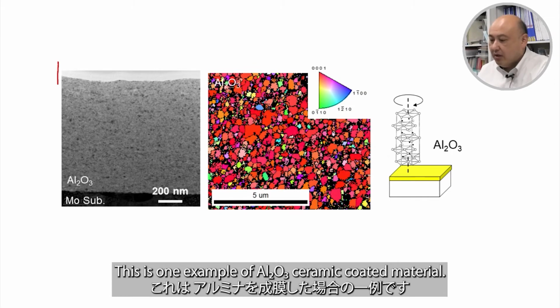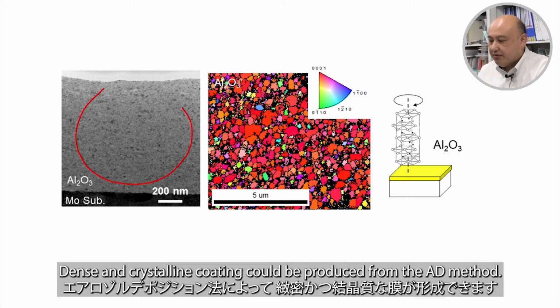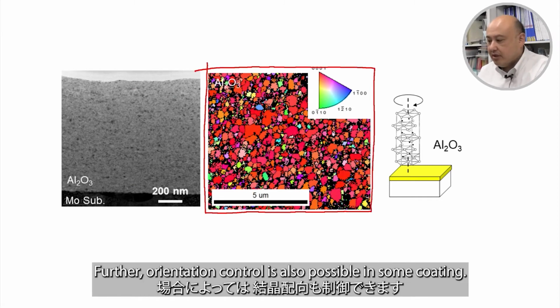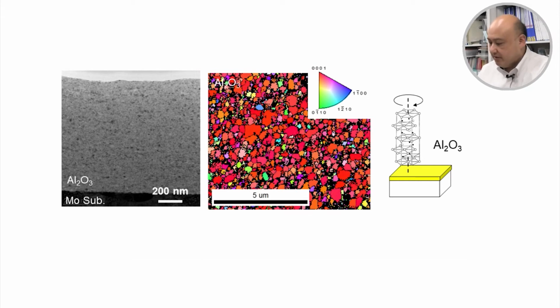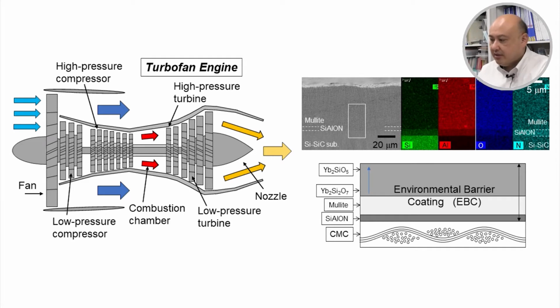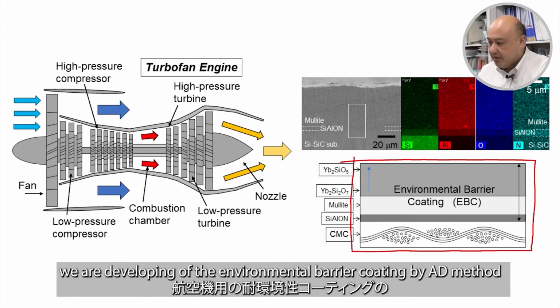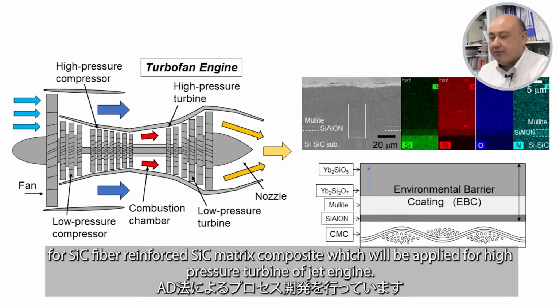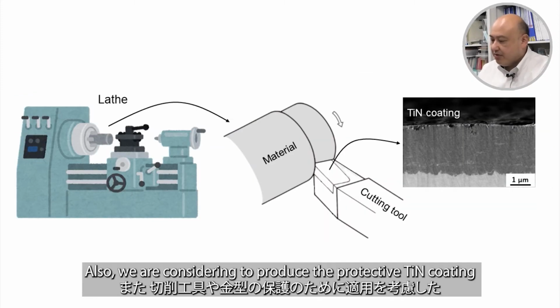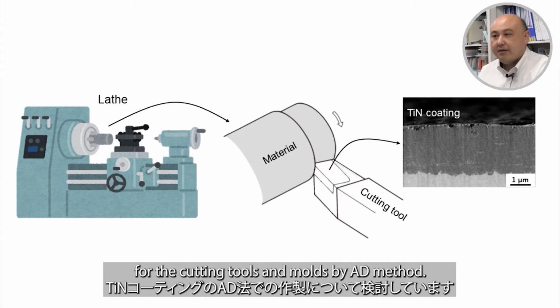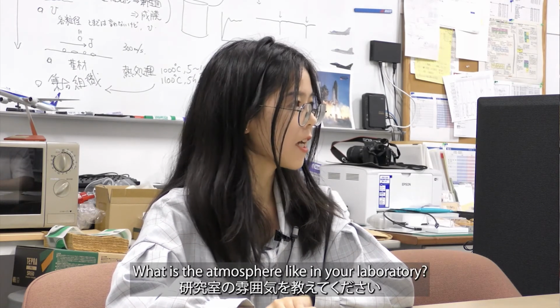And this is one example of an alumina ceramic coating material. Dense and crystalline coating can be produced by the AD method. And further orientation control is also possible in some coatings. By using such characteristics, we are developing an environmental barrier coating by the AD method for the silicon carbide fiber reinforced silicon carbide matrix composite, which will be applied for the high pressure turbine in this part of the jet engine. Also, we are considering producing protective titanium nitride coating for cutting tools and also molds by the AD method. So what is the atmosphere like in your laboratory?